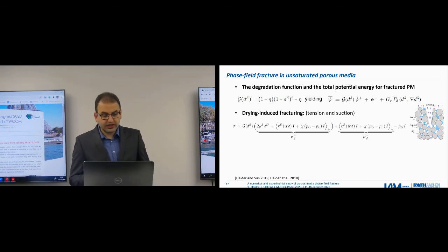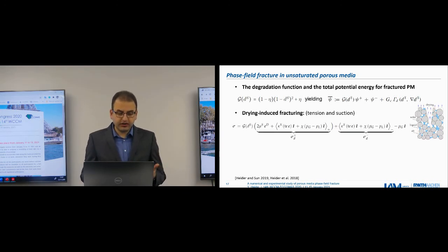Based on this, we can derive our stress tensor. So the stress would be simply the derivative of the energy with respect to the strain. And then we get this first relationship of the stress, which is in connection with the drying induced fracturing. You see that the degradation function is multiplied by the elastic energy, which is the positive one, and also includes the contribution of the suction.